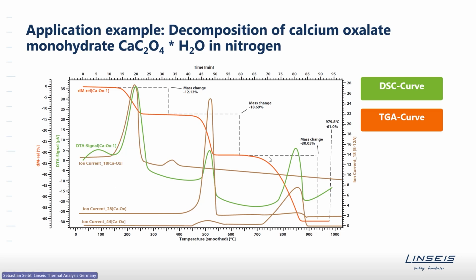And then you have 2 more steps where it loses carbon monoxide and carbon dioxide. In that example here, you can see these brown lines additionally to the orange mass change and the green DSC curve. These brown lines here are showing you the readout of a mass spec. So the upper line here is the mass trace of water, where you can see there's a loss of water, a big peak at the first place, then a little bit water loss here, just a tiny amount that you almost cannot see.